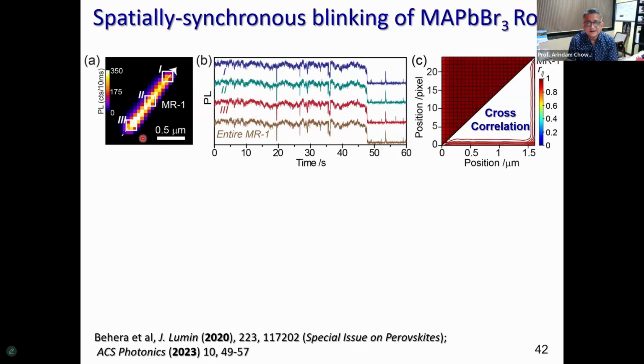If you look at the rods under the microscope and you collect a movie, this is a rod of about 1.5 microns here. If you look at the regions 1 to 2 to 3, about 1 micron separated, look at the fluctuations. They are highly, highly correlated. We developed methods to quantify this correlation, and I'm going to use the term blinking correlation, or correlation in blinking. It's a cross correlation function that you can generate along the length of the rod, which is a pixel by pixel correlation. And you can see it's all red.